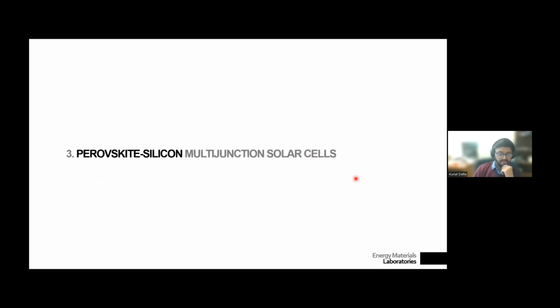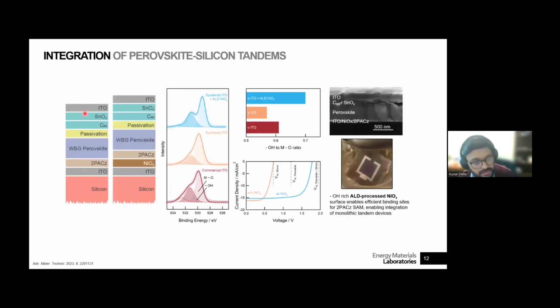All right, then we started to integrate these devices into multijunctions, so tandems. And the first one we looked at was the perovskite-silicon tandem solar cell. So this is the general stack of the device. It's a silicon heterojunction solar cell, an ITO recombination junction, that's the interconnection, and then basically a PIN device, the 2PACz, and the wide bandgap perovskite, passivation, C60. We replace the BCP with tin oxide, and you need that to protect the C60 from any damage during the sputter of this ITO layer.